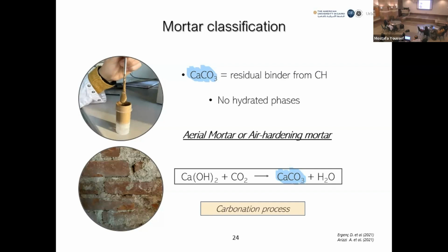I'm working with an air-hardening mortar, and this means that at the time when they decided to build the building, the main reactive part was represented by Portlandite, which is able to react with the CO2 present in the atmosphere through a carbonation process in order to form calcium carbonate, which is the main mineral that gives the strength to that kind of mortar. And this calcium carbonate is the same calcium carbonate that I was able to detect.